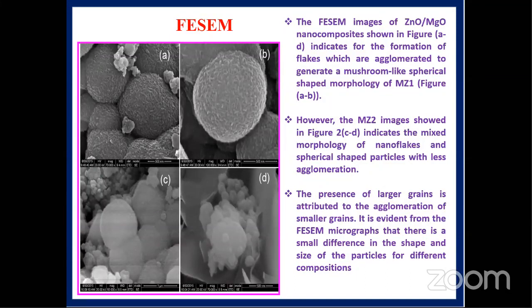You can see there is an image of the different ratios of this nanocomposite. A and B are the first ratio of this composite, MZ1. You can see how the grains are located. This figure indicates the formation of flakes which are highly agglomerated. It is a mushroom-like spherical shaped morphology. And C and D, you can see here, is the MZ2 nanocomposite, with less agglomeration. It also indicates a mixed morphology of nanoflakes and spherical shaped particles with less agglomeration. So from these images, the larger grain is attributed to the agglomeration of smaller grains. Once again, it is evident from the FESEM micrograph that there is a small difference in the shape and size of the particles for different compositions.